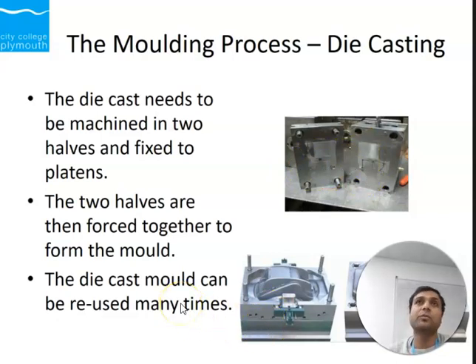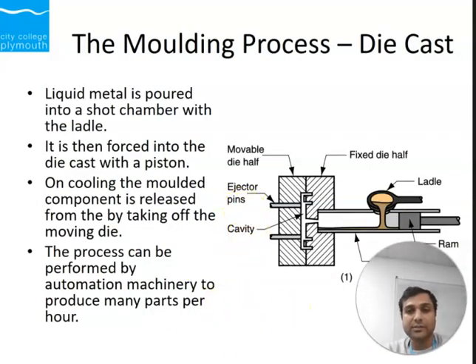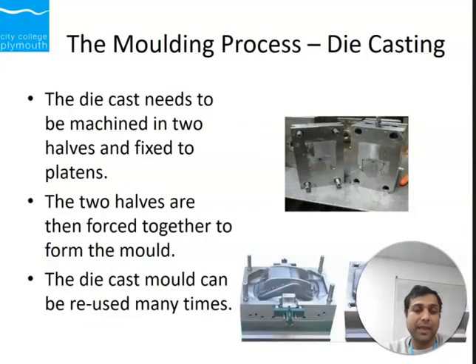The die cast can be used over and over again. The advantage of die casting as compared to sand casting is a very good surface finish. Sometimes we don't have to perform a lot of secondary finishing process. If you're producing thousands, 10,000, 20,000, it is more economical. It gives you good dimensional accuracy and good surface finish. Very thin sections can be formed, and sometimes we can accelerate the cooling. Rapid cooling is achievable. In sand, the cooling rate is slow. Metals are good conductors, so good cooling rate. The faster the cooling rate is, the smaller the size of the grain, which gives good strength.